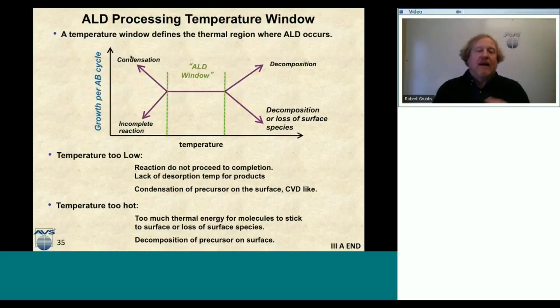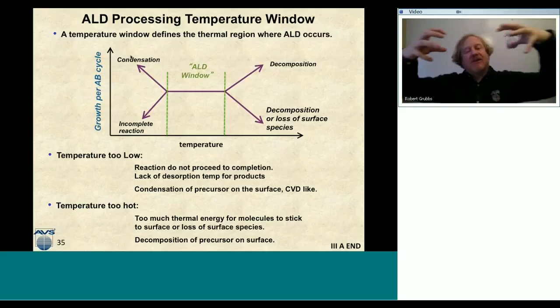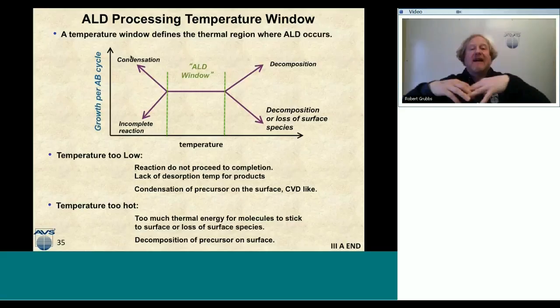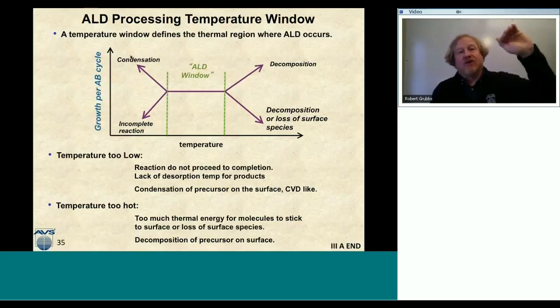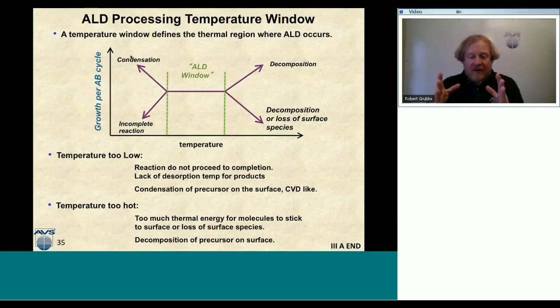If the temperature is too low, and I'm seeing this very large growth per cycle, I could actually get ALD chemical precursor to sort of condense into a liquid or a solid on the surface. So as I do my AB cycles, I'm actually seeing a larger growth per cycle as temperature goes down, because I have more of this liquid or this solid that I've sort of condensed onto the surface. The opposite of that is that there's just not enough thermal or kinetic energy to make the reaction drive to completion. And so when the temperature is too low, I get a very low growth per cycle because of an incomplete reaction, because there's just not enough thermal energy for the reaction to get over the activation energy into the transition state and into the chemisorption well.